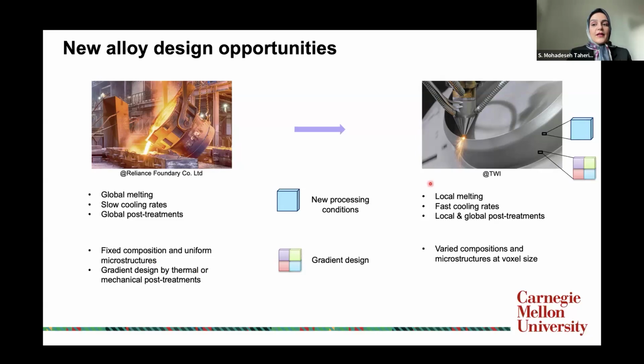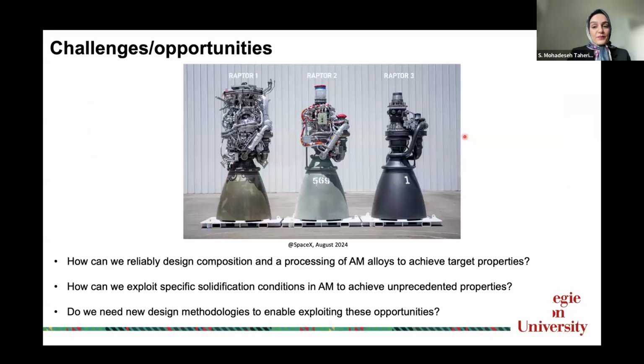Here, however, at the voxel size resolution during printing, you can tune the feed rate of the powder from these tubes. Therefore, you can change the composition and you can change the heat. Therefore, you can change the macrostructure. So at the voxel size resolution, you can make gradient alloys.